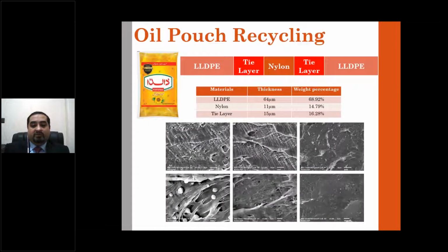So keeping in mind this area, we started working on trying to recycle these multi-layered structures, but we ran into some problems. What were those? We took the oil pouch, one example shown to you over here. The internal morphological structure basically consists of LLDPE with a tie layer, which is LLDPE grafted maleic anhydride, used as a compatibilizer in polymers and also as a tie layer. Then it has nylon present in between them, and the weight percentages are shown to you over here.